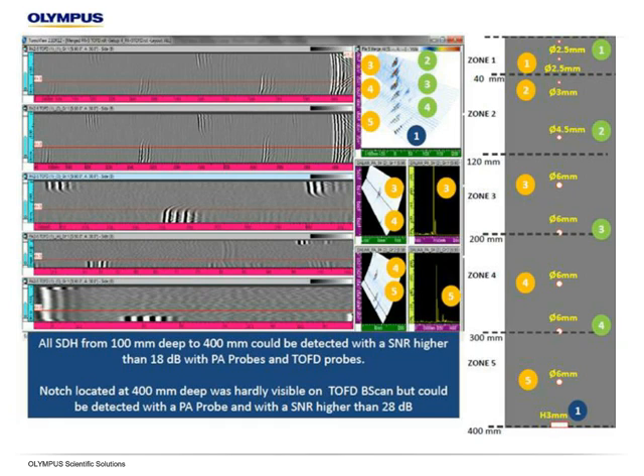And that's really an area that we focused on the phased array as well, because it was the one indication way down at 400 millimeters that had a little bit lower resolution on the TOFD display. So we're able to get full volumetric coverage except for the very top, which we covered with a magnetic particle inspection that was done anyway to cover that zone with a very high signal-to-noise ratio.